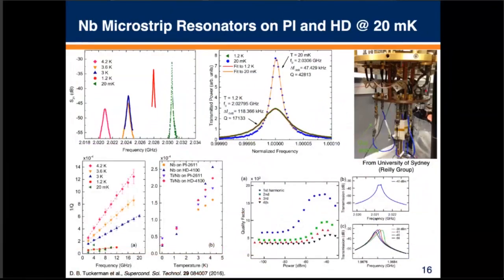So some of those early resonators that we did, we were able to send out to some colleagues at the University of Sydney and have them characterize these resonators down to approximately 20 millikelvin. And you could see a couple of interesting things. The resonant frequencies would shift. That's due to a continued change of the kinetic inductance that causes the shift of the resonant peak. And then you can see the Q continued to sharpen as we went even lower. So that provides some good evidence that these might be useful structures even in the millikelvin regime.